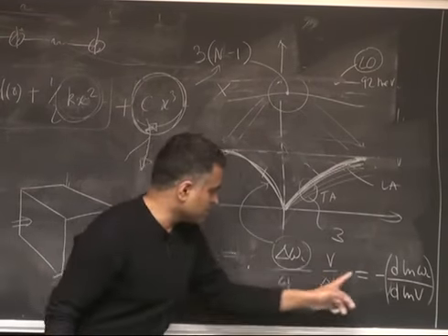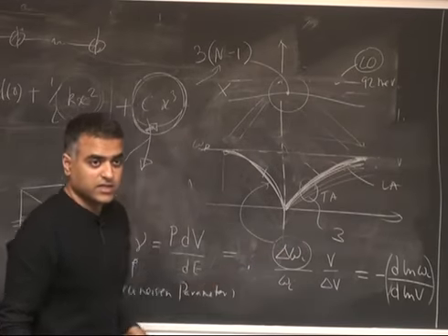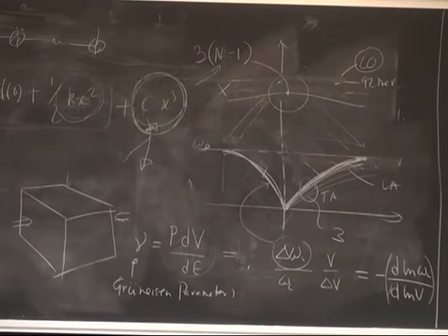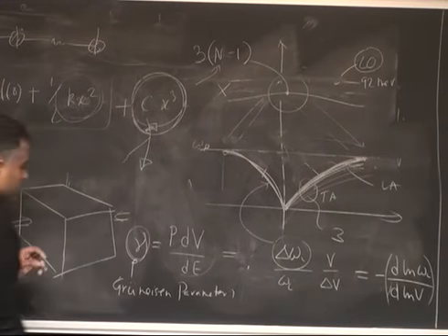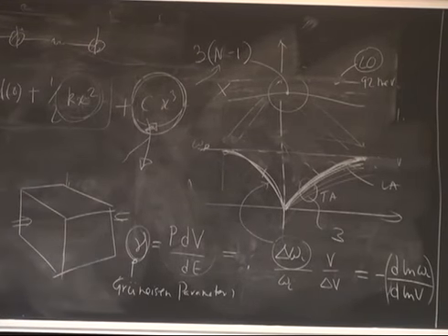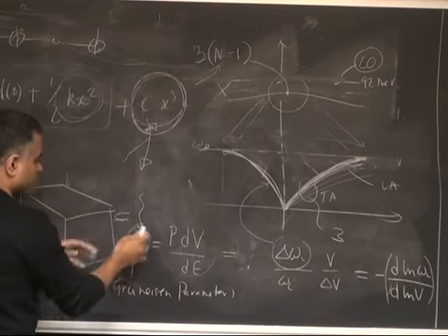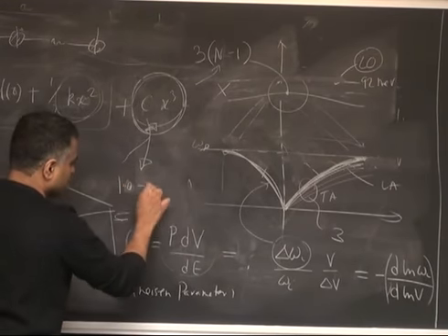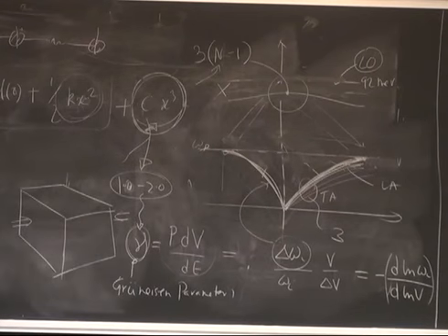D natural log gives you d by that, right? That's how it's written. It's a Grüneisen parameter, and it's a measure of this anharmonicity, and it plays an absolutely critical role in thermal conductivity. So you can take this microscopic picture, calculate it, or do a physical measurement, calculate it or measure it, and you will end up with something like roughly 1.0 to 2.0. That's the range of the Grüneisen parameters.